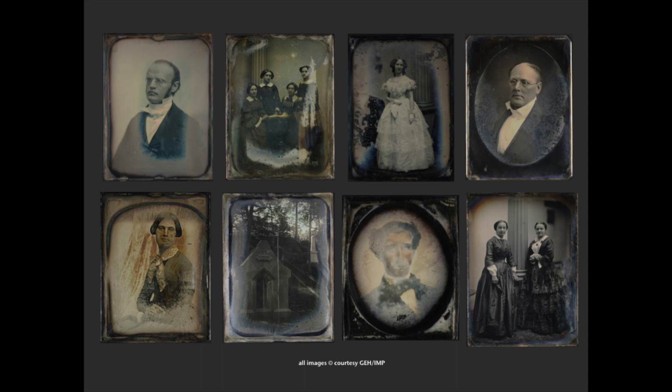They lived their lives in storage in boxes. There is evidence, of course, that they were exhibited. If you look at most of the plates, they have perimeter tarnish on them. That tells me that in the Daguerrean era, when they're trying to show the best of their work to their clientele, they have the plates hanging on the walls on view. And this is where the perimeter tarnish in reaction with the brass mat has occurred. I cannot imagine they would have looked like this on their studio wall.